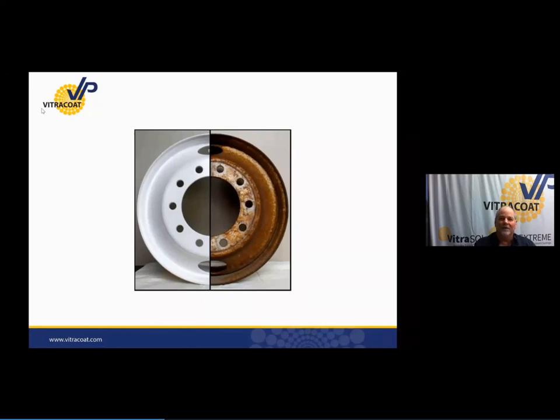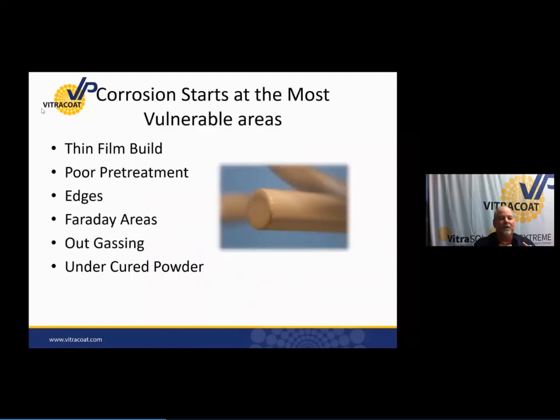But I want to take this conversation another step. If you want to get an idea of how your part's going to hold corrosion, you need to look at all of the elements of that part. Corrosion starts at the most vulnerable areas where you've got the thinnest amount of film built. Poor pretreatment, Faraday areas, outgassing, even undercured powder. Those are kind of obvious, but where corrosion typically starts is on edges, shown here in this wire. That edge has less than 0.2 of a mil on it, while the wire part has over 3 mils. My corrosion is going to start on that edge.